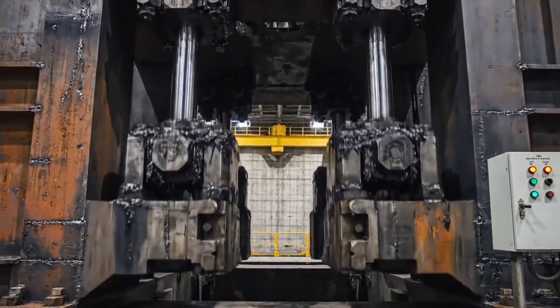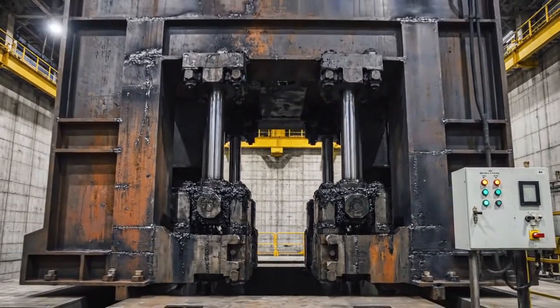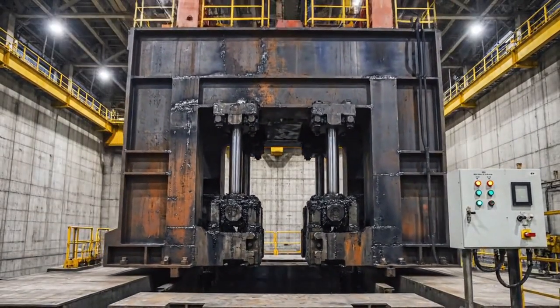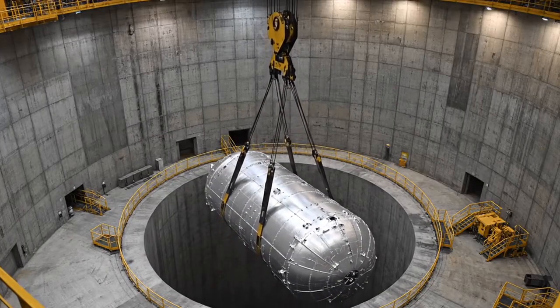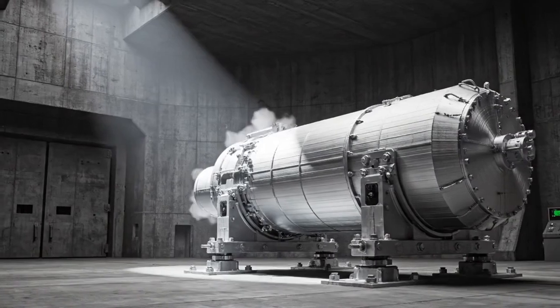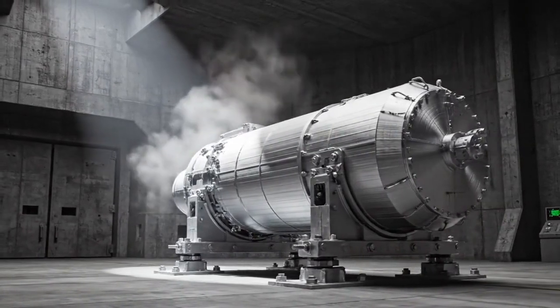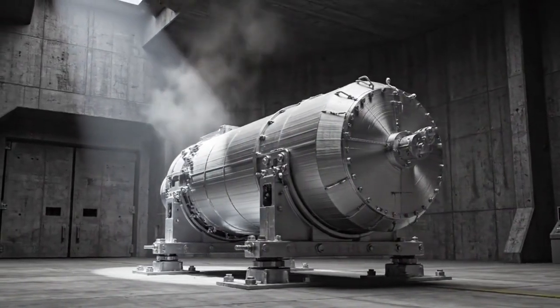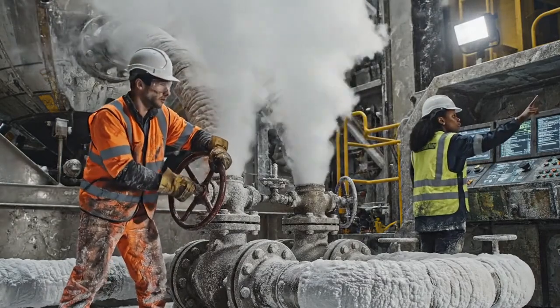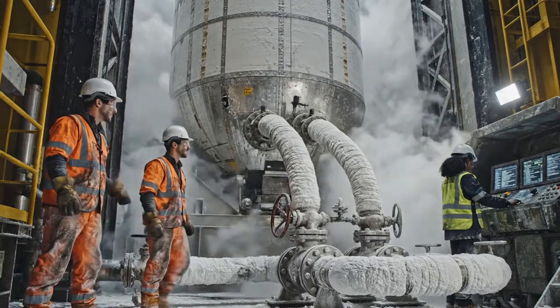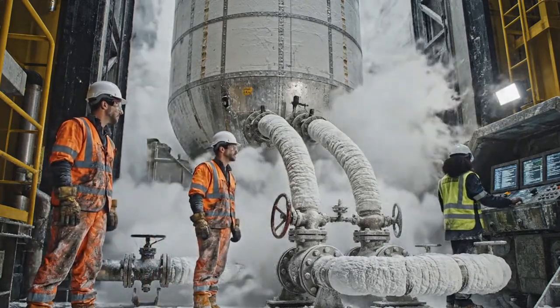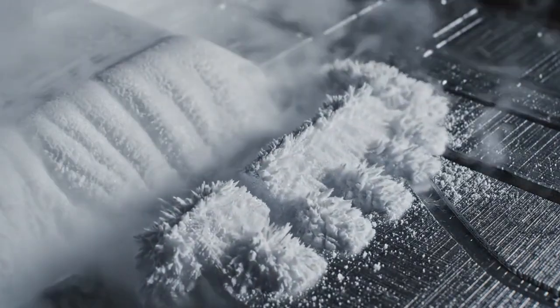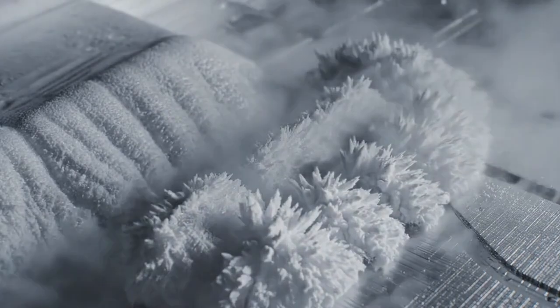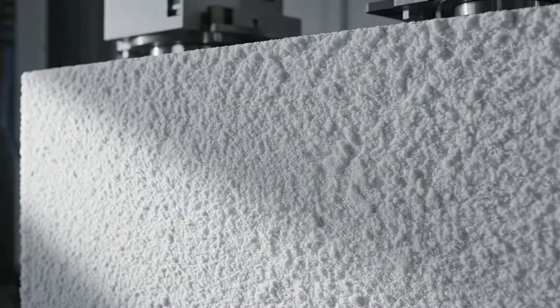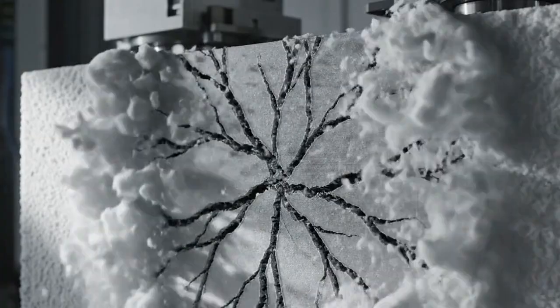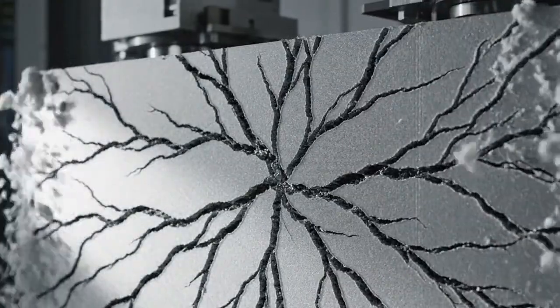Following structural validation, the ultimate physical threshold is evaluated through extreme mechanical and thermodynamic stress testing. The most critical of these is the cryogenic proof and burst test. The fully printed propellant tank is transported to an isolated, heavily fortified testing bunker. Here, engineers pump thousands of gallons of liquid nitrogen, or in some iterations, subcooled liquid oxygen, chilling the aluminum alloy down to a sustained -196 degrees Celsius. This induces a severe cryogenic thermal shock, drastically altering the fracture toughness and ductility of the printed metal.